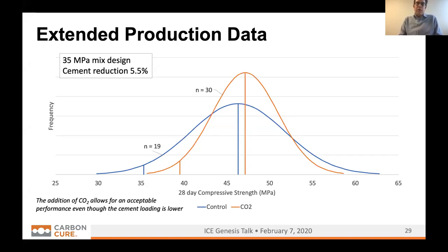Since this is a 35 MPa mix design, the focus of the producer will actually be at the lowest end of the production. Statistically, you'll have a 95% chance of any batch being over 35 MPa. So if we even highlight the difference between where the CO2 batch ended up, we have probably evidence we can take out even more cement if the producer wanted to and didn't otherwise impact things like the way the concrete looked or finished. So the producer is very happy with this adjusted mix design.